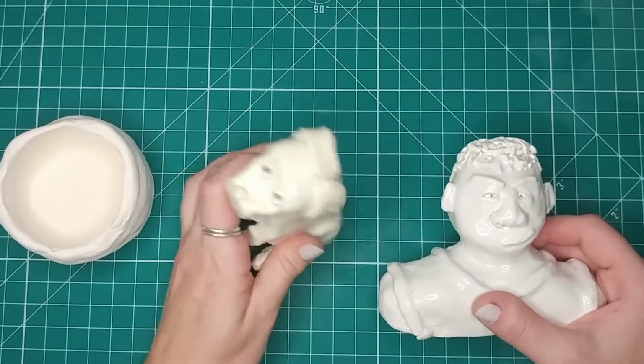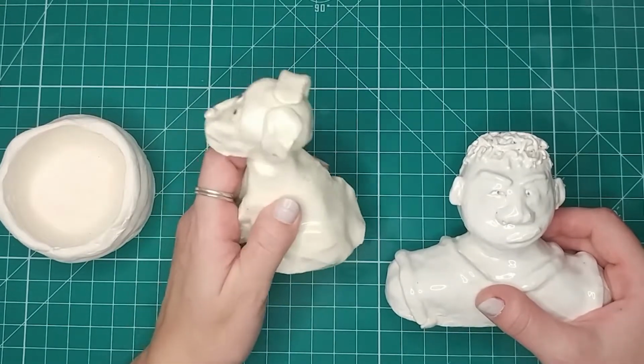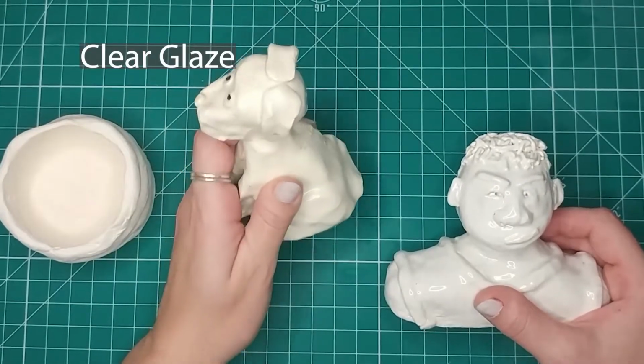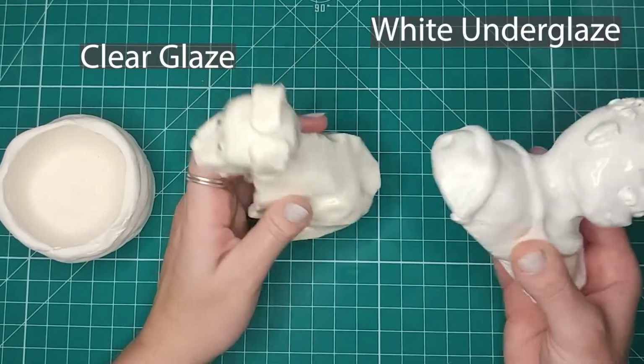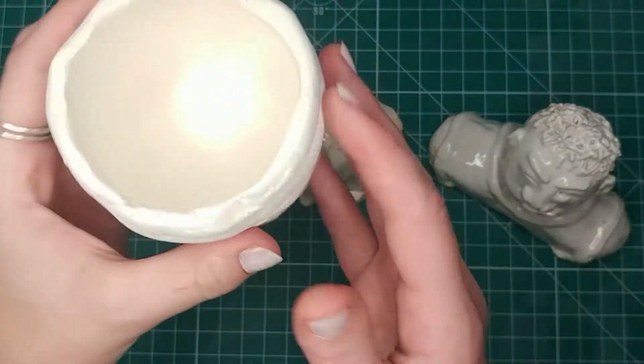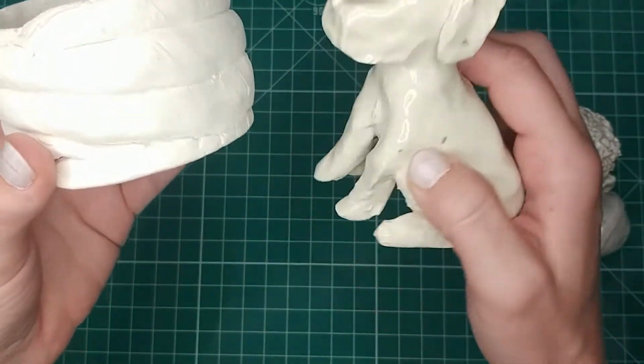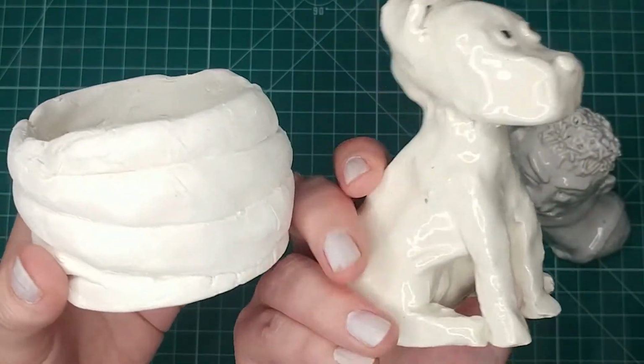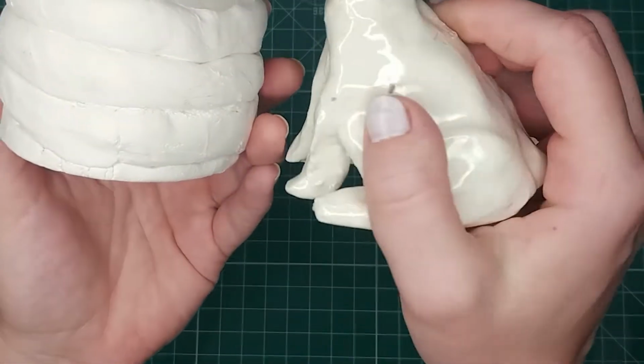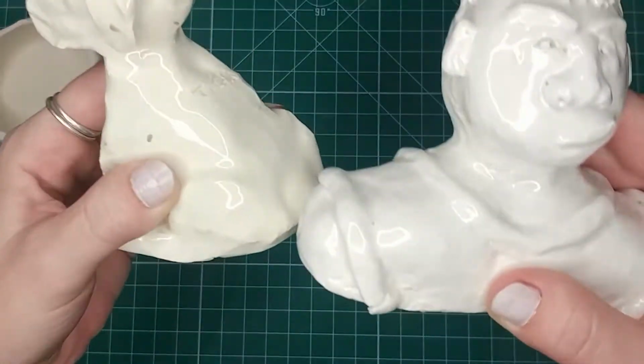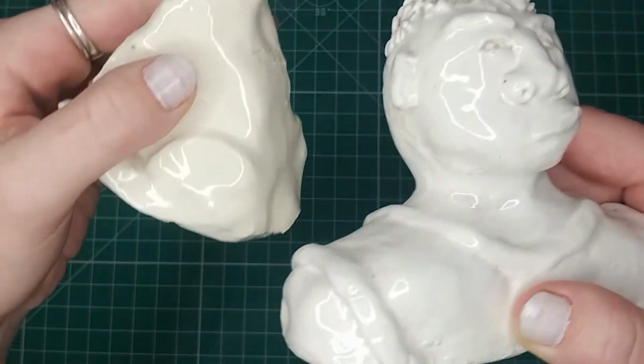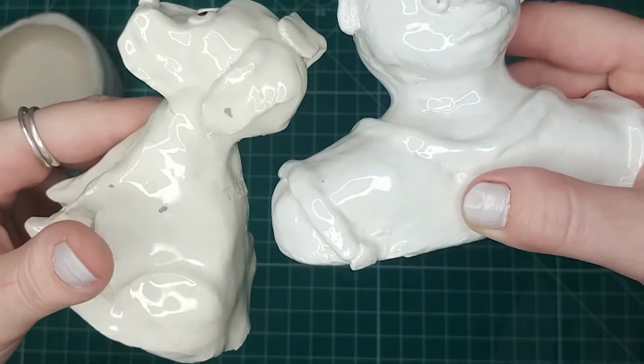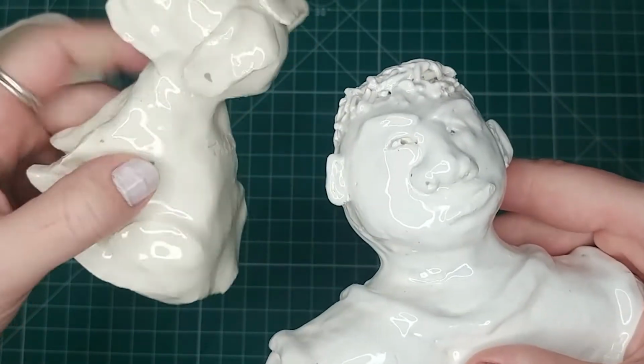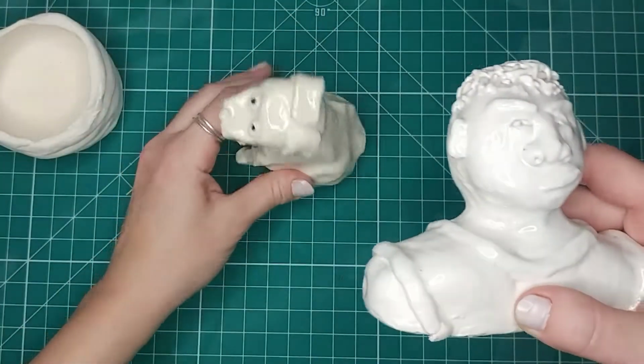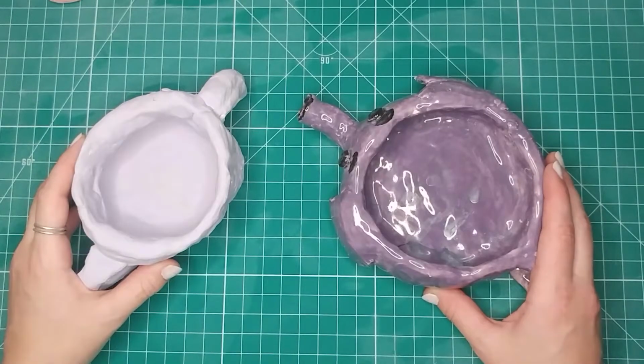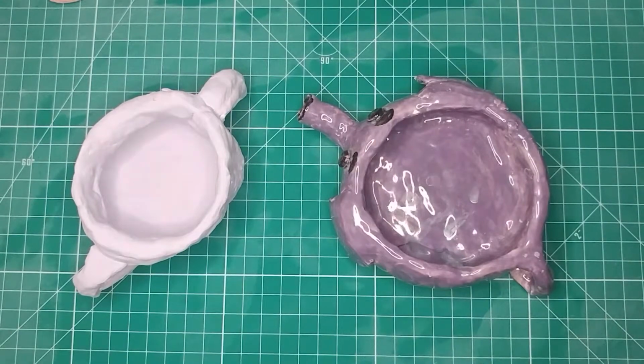Now let's check out the difference between what it looks like when you add clear glaze only to your bisqueware and what it looks like if you add white underglaze and clear glaze. So for a starting point, this is our unglazed bisqueware. This is what it looks like if we add clear glaze only. The color stays exactly the same, but it becomes shinier. If we add white underglaze and then the clear glaze on top, you can see that we do get just a slightly brighter, truer white than the off-white of our bisqueware. Artist's choice.